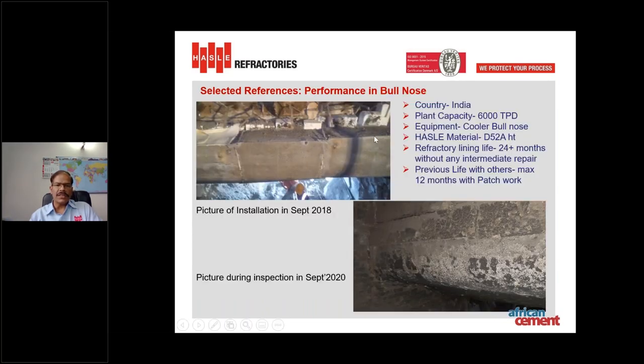Coming to the cooler side, this plant is from India with 6000 TPD capacity, and they were facing a problem with the refractory lining in the bullnose area. They were getting only 12 months of life with some patchwork in between. We studied and supplied our D52A castable and they were able to achieve 24 months of life without any intermediate repair. This picture is from the September 2018 shutdown, and this one is from after September 2020. As they had to run the plant for the next 1 year, they replaced this with new castable.